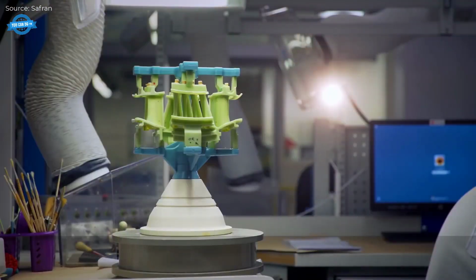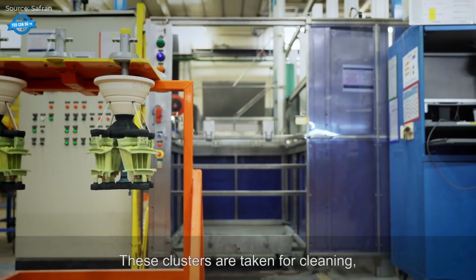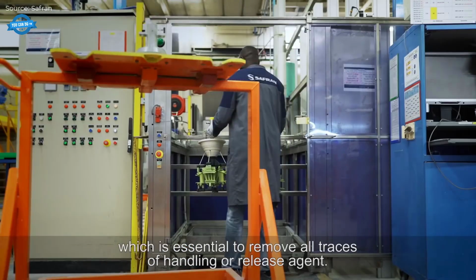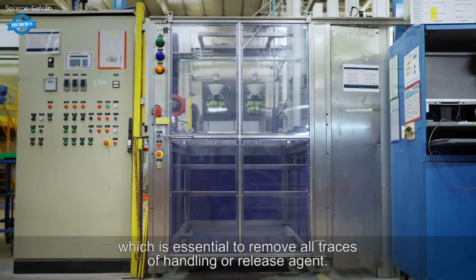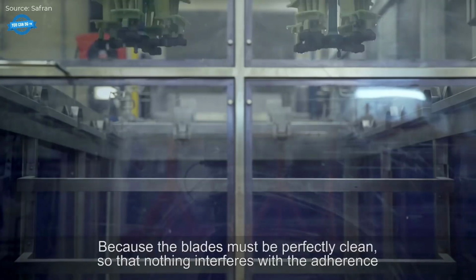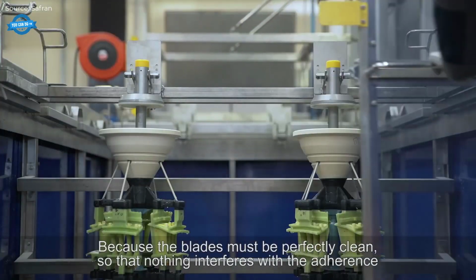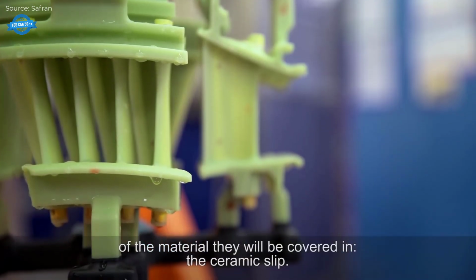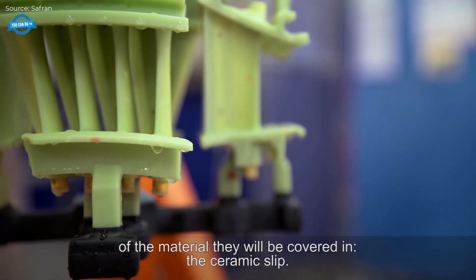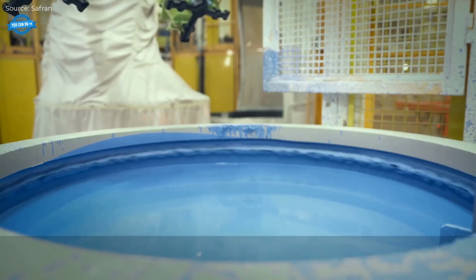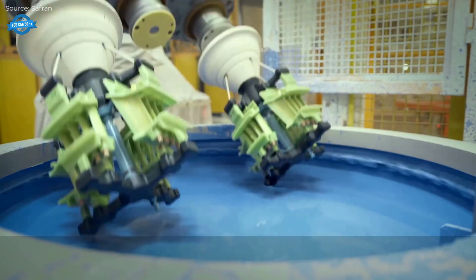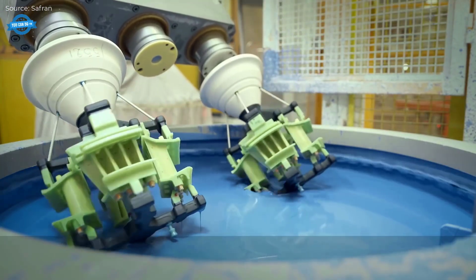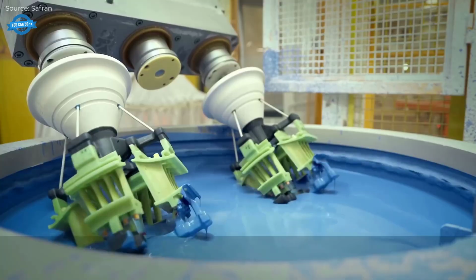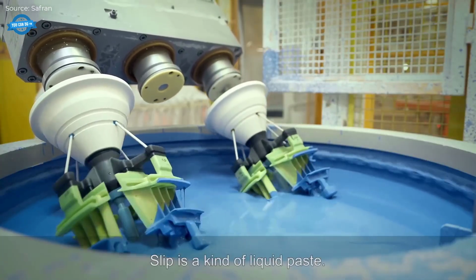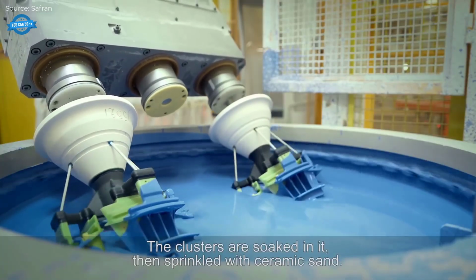The wax replicas are grouped into clusters, then cleaned meticulously to remove any contaminants. Cleanliness is critical to ensure adherence of the ceramic coating applied in the next steps. The clusters are then immersed in a ceramic slip, a liquid paste that creates a ceramic layer over the wax. A ceramic shell is gradually built up by alternating dips in ceramic slip and ceramic sand application. This process is repeated until a sufficiently thick shell is formed.